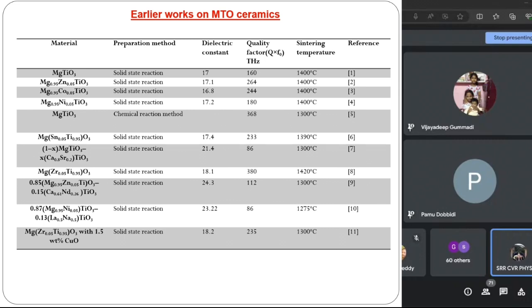So this is our challenge. Now if you look here, 1400 degrees C is the temperature. What we proposed is that if we can reduce the processing temperature without compromising your dielectric constant and quality factor, in the left hand side two columns, if we can do that without compromising the dielectric constant and the quality factor, and reduce the processing temperature, that is the challenge that we have taken in this study.